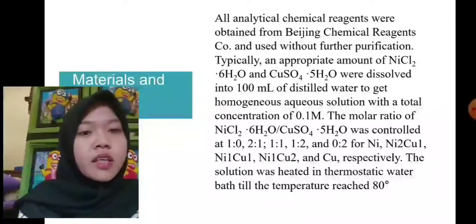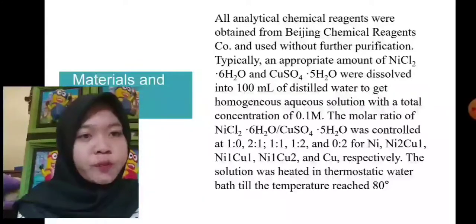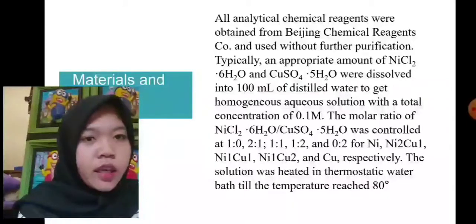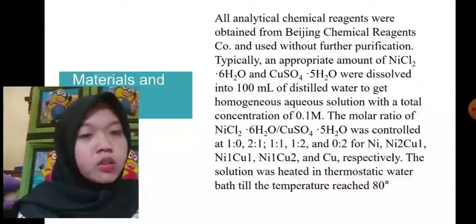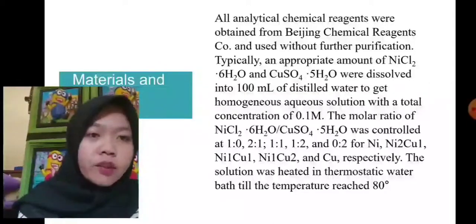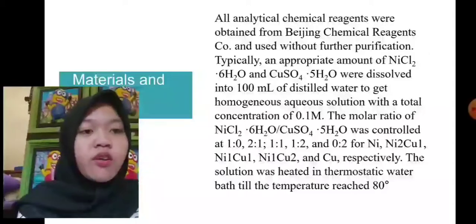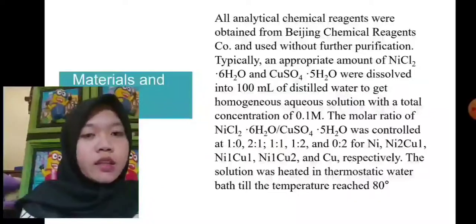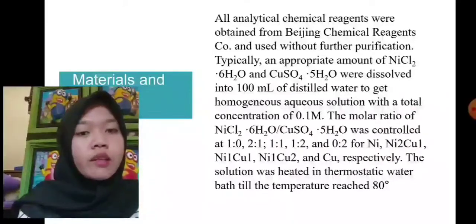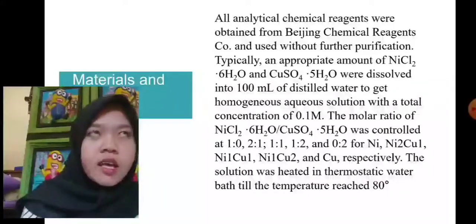concentration of 0.1 molar. The molar ratio of nickel chloride 2 to copper sulfate 4 was controlled at 1:0, 2:1, 1:1, 1:2, and 0:2 for nickel 2 copper 1, nickel 1 copper 1, nickel 1 copper 2, and copper, respectively. The solution was heated in a thermostatic water bath till the temperature reached 80 degrees.